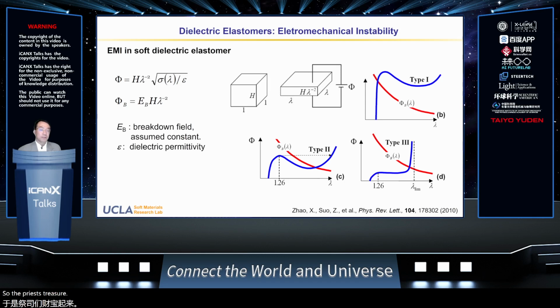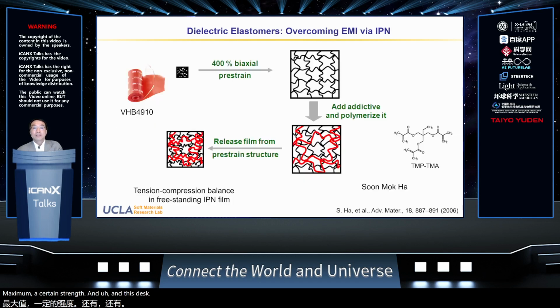So the pre-stretched film shows a different stress strain behavior. It allows you to drive the film to a much larger strain at the lambda limit here. Okay, so this is how the pre-stretching works for dielectric elastomers to boost the maximum actuation strain and the stress. So pre-stretching works beautifully, but it's practically problematic because a highly pre-stretched elastomer film will fatigue over time. So they generally have limited shelf lifetime.